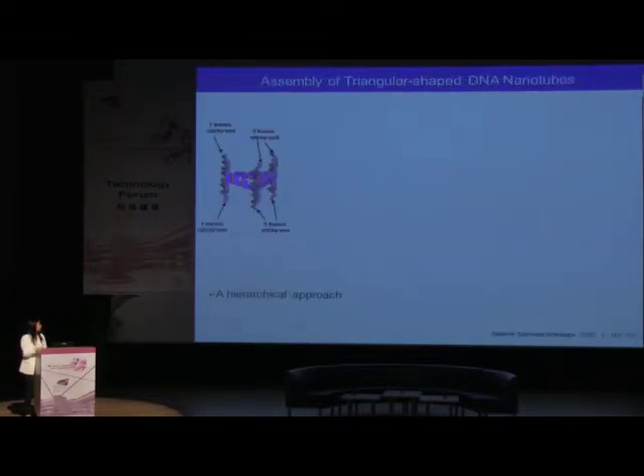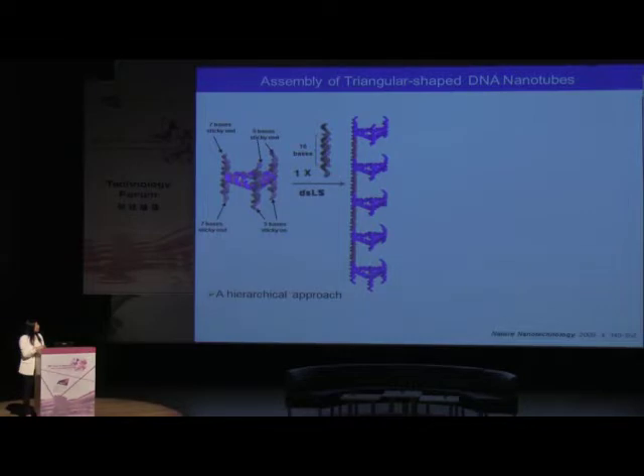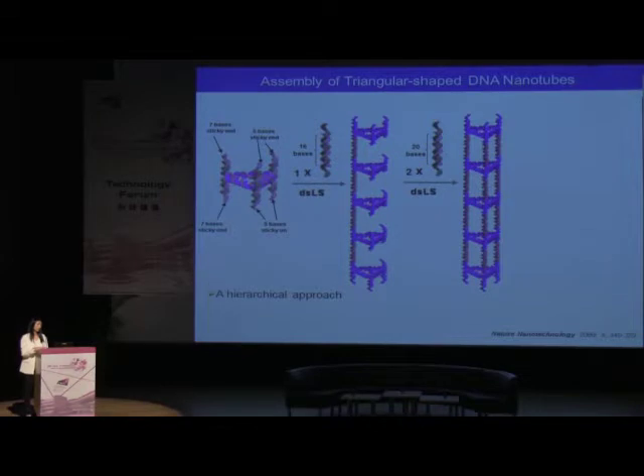And to generate a well-defined or controllable nanotube, basically we're using a hierarchical approach. So here, you can see that one side of the strands with the sticky end is 7 bases long, and the other 2 sides have shorter sticky ends, 5 bases. So to form a tubular, one-dimensional nanotube, we add the double-stranded linking strand here, heat up the sample and cool down. So basically, the double-stranded linking strand will cohere to the longer side first to form this linear assembly before the cohesion of the other 2 sides. And we found that using this approach, we can have a high percentage yield of the long tubular structure, and we can also prevent the cross-linking.